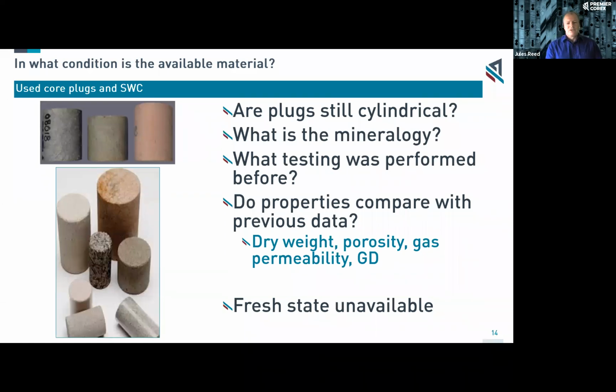And so you might want to do testing for that before you start using the samples. Also, another mineral that you might want to think about is smectite. Of course, smectite is a swelling clay. We then need to consider the impact of cleaning and resaturating with water. We need to make sure that we've got a good handle on our water salinity, and that it's not causing problems with those clays through the various cycles of testing.